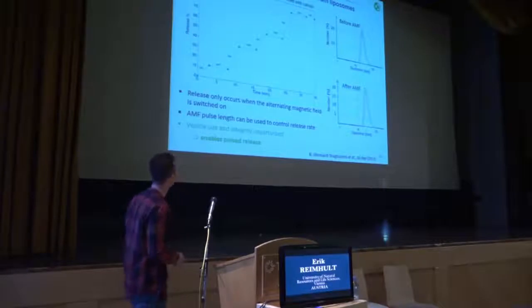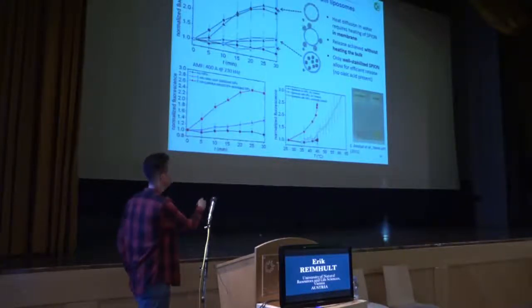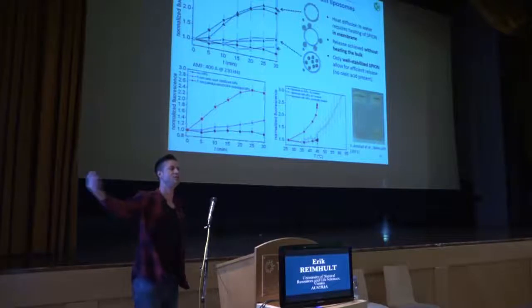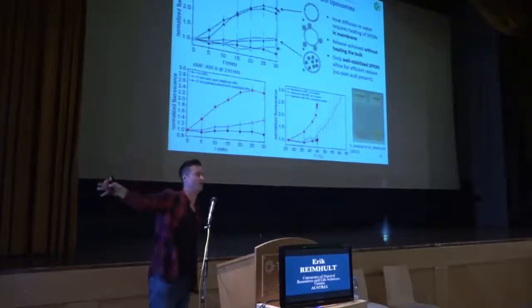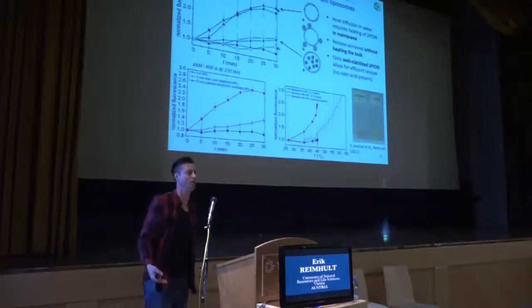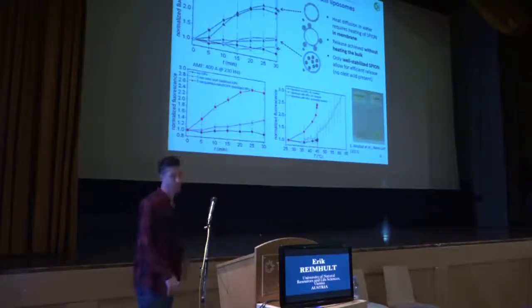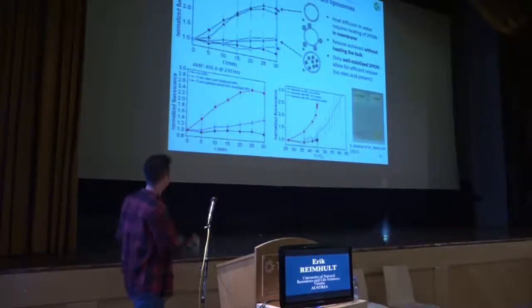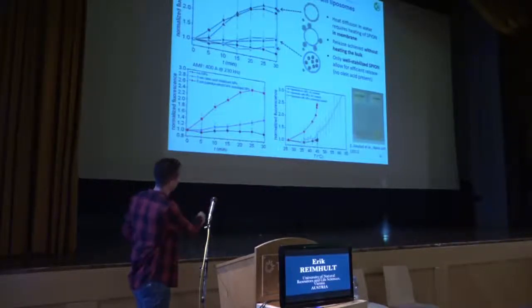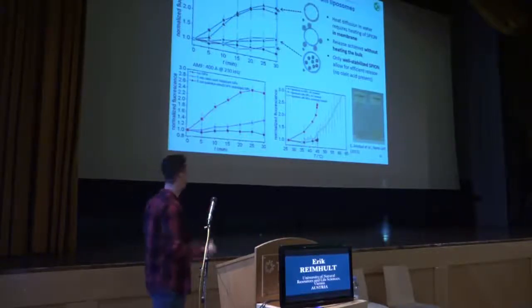In the end, one can show which nanoparticles actually fit into lipid membranes, what sizes they have to have, and this is quickly showing that if they're too big, they cluster and go out and you get micelles instead. If they're small enough, we can put them inside the membrane at controlled concentrations. If we do that, we can then use magnetic fields, like I explained in the hypothesis: we switch the magnetic field on, we release some drug, we switch it off, there's no drug release, on, off, which makes it possible to arbitrarily release drug wherever and in what amounts I want, at least in a test tube. Maybe not in the rabbit, we haven't tried, we'll see.